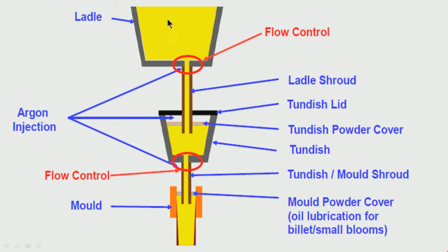So, the Ladle is getting emptied. On top of the liquid steel, what is there? There is a slag, because this slag was generated during the secondary refining processes. During the different secondary refining processes, we need slag, so slag was there at the top of the liquid steel. So, what does slag contain? It contains oxides: calcium oxide, some amount of MgO, and a small amount of Al2O3. Maybe a small amount of iron oxide, which is not desirable, maybe manganese oxide, and some amount of SiO2, though these are not desirable. So, the slag contains only oxides.